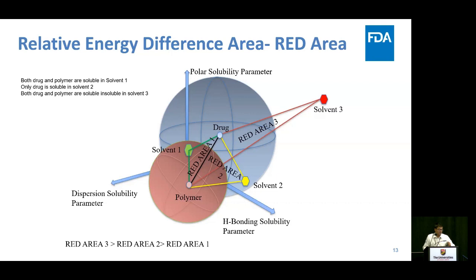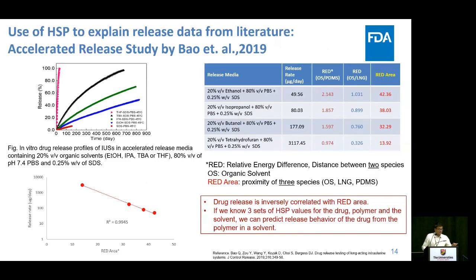So we use this new term, RED area, to analyze already published data. This is released data from a paper from Dr. Barges' group at UConn. We analyzed this data and found that the release rate is inversely proportional to the RED area. So this gives us a very good sense of how useful HSP analysis can be. If we only know the HSP values of the drug, polymer, and the solvent, we can essentially speculate or predict the drug release behavior of a polymer within a solvent.